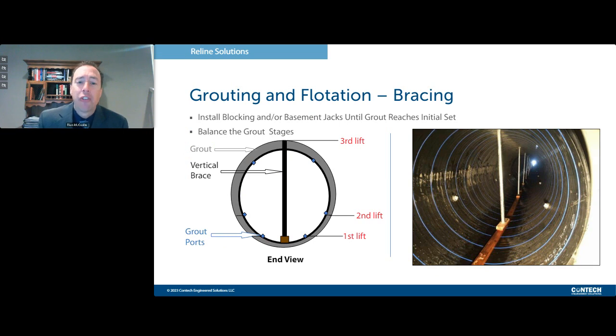If you don't have easy access to water and the liner pipe is enterable, so you can enter it, we can actually pre-install grout ports. If you look at the picture on the right, you can see the white dots. Those are grout ports that are pre-installed at the plant. Here they're at the 5 o'clock and the 7 o'clock position, and they also have one at the 12 o'clock position. Those are going through the pipe wall and bracing against the host pipe crown. And essentially it's holding down the liner pipe while the grouting process occurs.